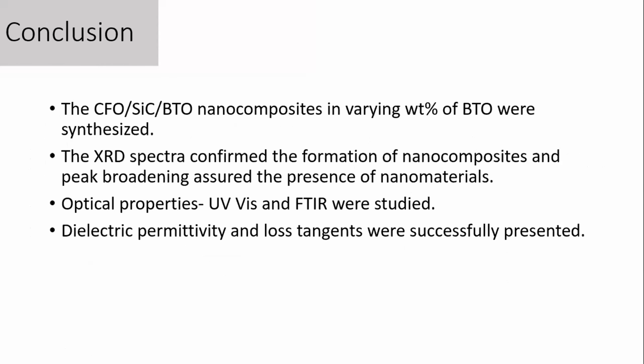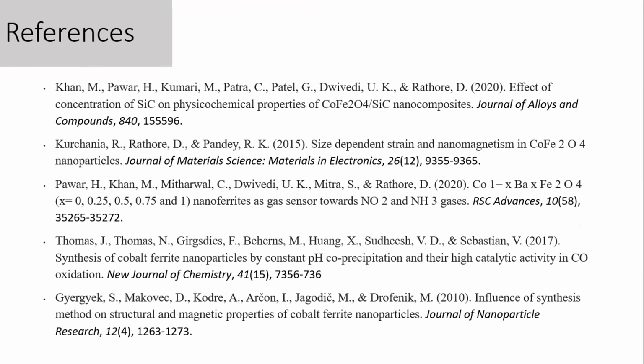So I would like to conclude my presentation here. We successfully synthesized CFO, cobalt ferrite, silicon carbide, barium titanate nanocomposites at varying weight percentage of barium titanate. The XRD spectra confirmed the formation of nanocomposites, and peak broadening assured the presence of nanomaterials. Optical studies were showcased here, and the dielectric permittivity and loss tangents were also successfully presented. Thank you so much. I'm done speaking.